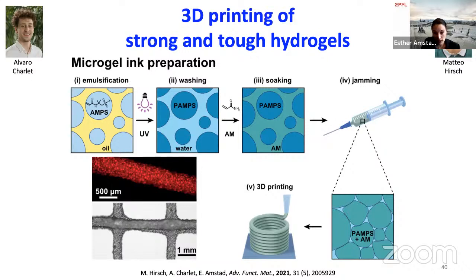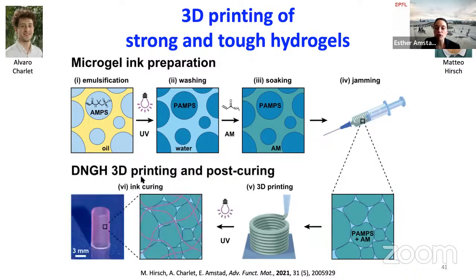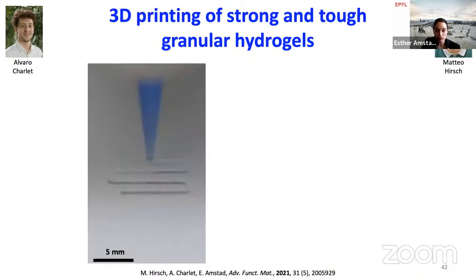But what was, and this has been done before, this is nothing new, but what was new is that here you still have these unreacted reagents within these particles, and we use them to form a percolating network that interpenetrates the particles and covalently cross-links them. And the important point is that this cross-linking step happens after the 3D printing process has been completed. So you don't form weak connections between subsequently deposited layers, but you get an integral percolating 3D network that imparts strength and stiffness to the material.